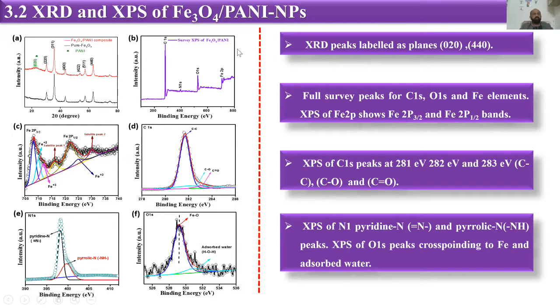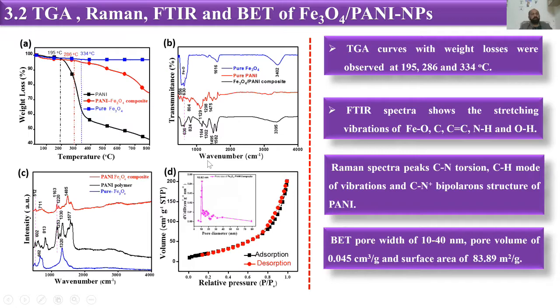Then we have done the TGA, Raman, FTIR, and BET of our Pani nanocomposite materials. We have again got the TGA with the maximum weight loss at about 195, 286 and 334 degrees Celsius. Then we have got the FTIR spectra for our Fe3O4, Pani and Fe3O4 Pani composite, and we got the desired peaks for our system. Similarly, we have done Raman spectroscopy, and again we have got the related peaks for our system. We have done BET analysis for our Pani composite.